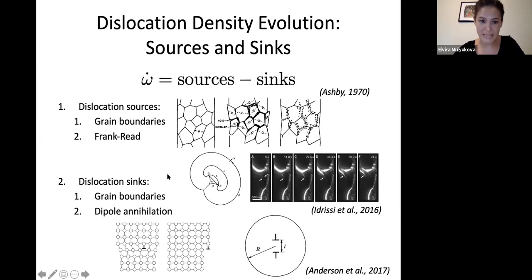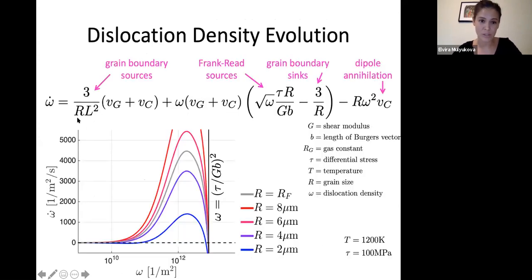Okay, so putting all of these mechanisms together into the evolution of a dislocation density, this is shown here. I'll explain what these different terms mean. I explained these four sources and sinks. This is the evolution of our dislocation density through time. Here's our source through grain boundaries. R here stands for some typical grain size. The reason it scales inversely with grain size is that the efficiency of this source depends on how much grain boundary you have, so this is basically your grain boundary density. The rate at which the dislocations can then leave the grain boundary and move away, to allow a new dislocation to form, is dictated by the velocity here, which is both glide and climb. Here's the Frank-Read source. As I said, the Frank-Read depends on the stress that is applied.